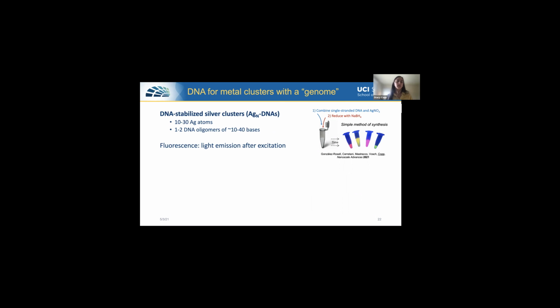And they're stabilized by 1 or 2 or maybe even 3 short pieces of single-stranded DNA. That's what oligomer means. It means a piece of single-stranded DNA. So not the double-stranded helix on the previous slide, half of that double helix. These are very easy to make. I'm a physicist, so I don't really do complicated chemistry. We can combine DNA with a silver salt, and then after some short amount of time, we can add a chemical that's called a reducing agent, and that catalyzes the formation of clusters.